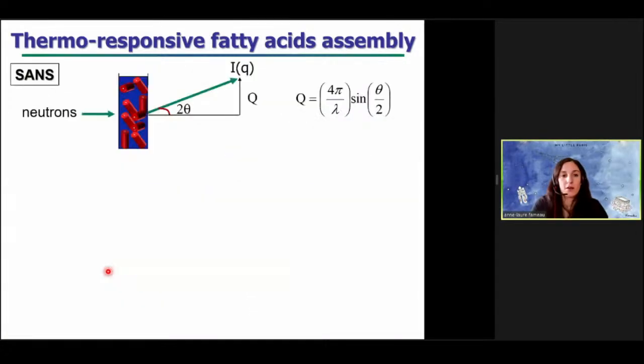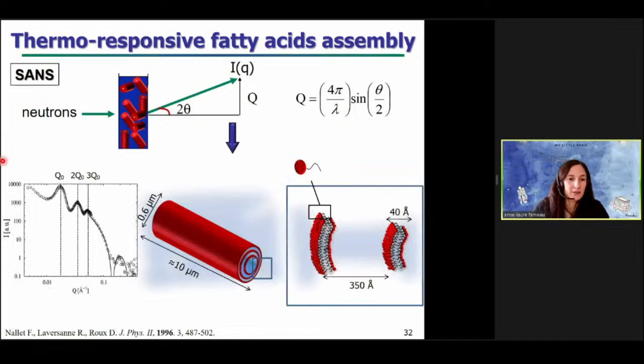To determine the tube structure, we use small angle neutron scattering experiments. In a small angle neutron scattering experiment, the neutron beam is scattered by the tube solution, and you just measure the evolution of the intensity as a function of the wave vector q. This wave vector q just depends on the scattering angle here and on the wavelength. Here you can see the scattering curve obtained for the tube solution, and you can see on the scattering curve the presence of three peaks, three Bragg peaks.